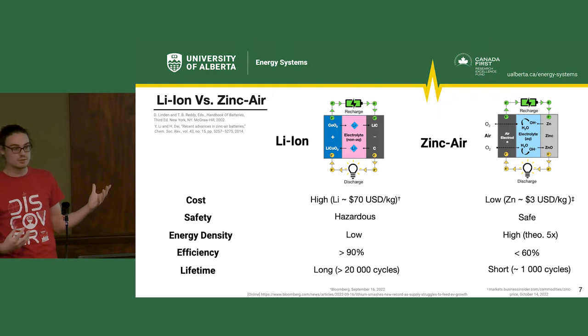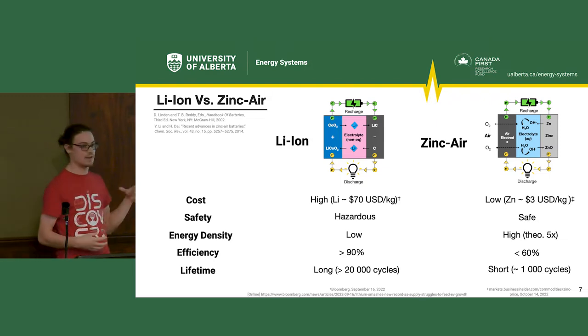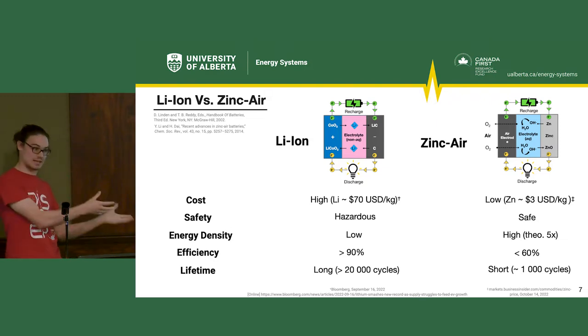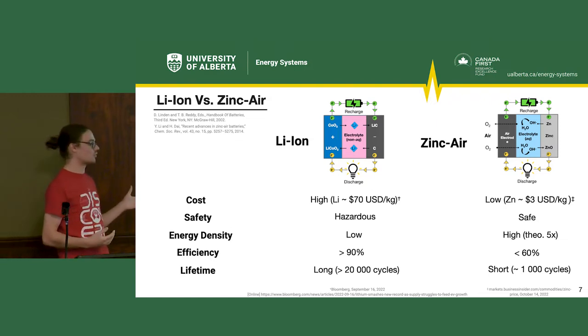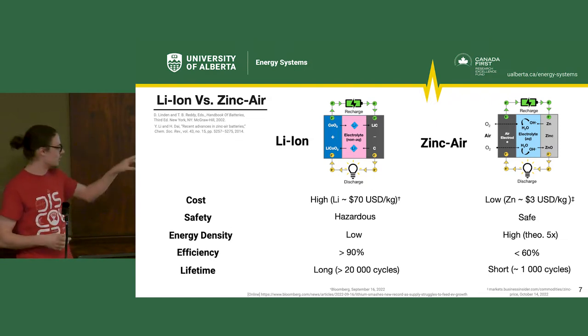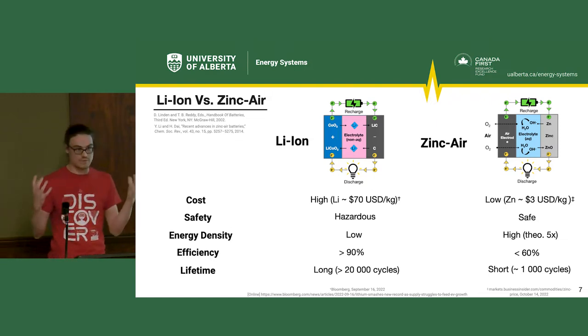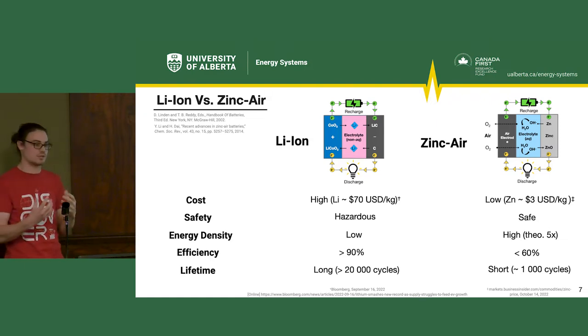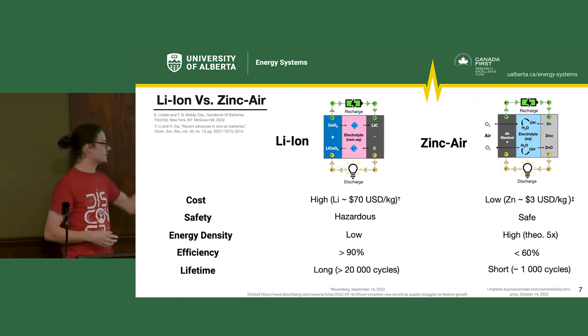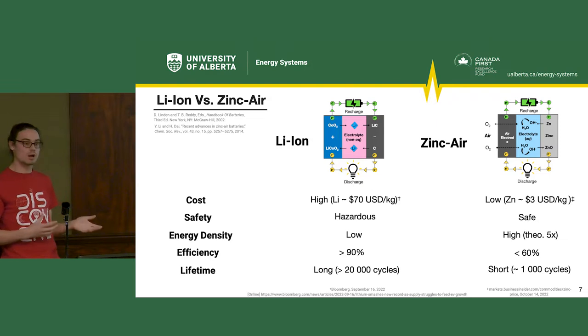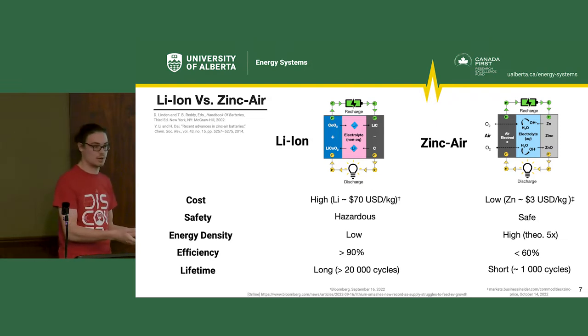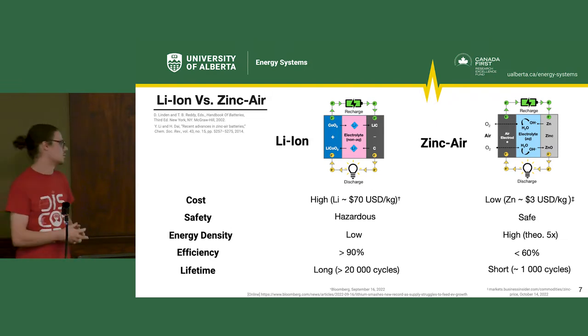Another thing is safety. Lithium-ion batteries don't have any water in them because lithium is reactive with water. And as a result, they have something that's more flammable. So that electrolyte there in pink is going to, if it ruptures, can cause those fires for lithium-ion batteries. Whereas zinc is fairly stable in water, so we can use a water-based liquid. And so it's a lot safer.